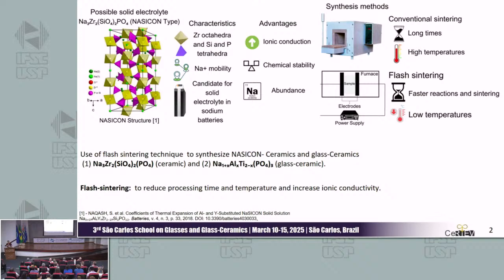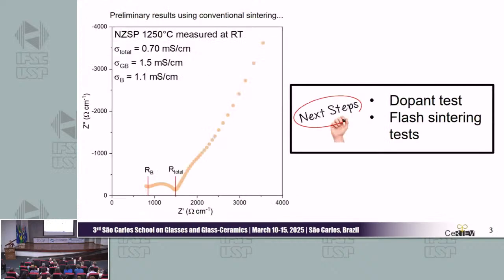And the first results using conventional sintering for the ceramic show a total ionic conductivity of 0.7 millisiemens per centimeter. The next step will be to test flash sintering and dopants in this system. Thank you.